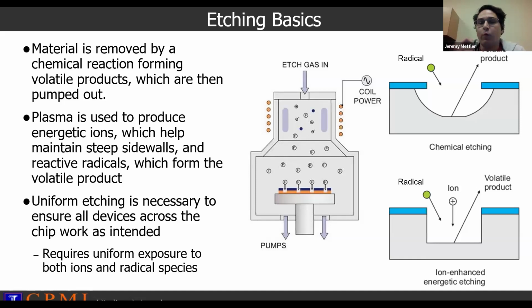And it's the work of both the ions, which provide the anisotropy, and the radicals, which actually do the etching. They produce the volatile product that allows you to remove material from the wafer surface. In the case of a silicon etch, for example, you might use fluorine radicals to form SiF4, which is then removed. And the key is that you want to get etching to proceed uniformly across the whole computer chip. You want to make sure that the devices near the edge of the silicon wafer work just as well as those near the center.